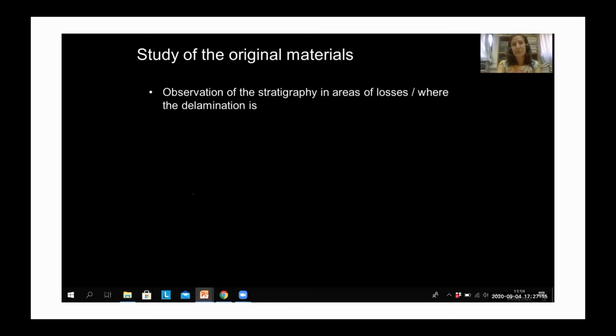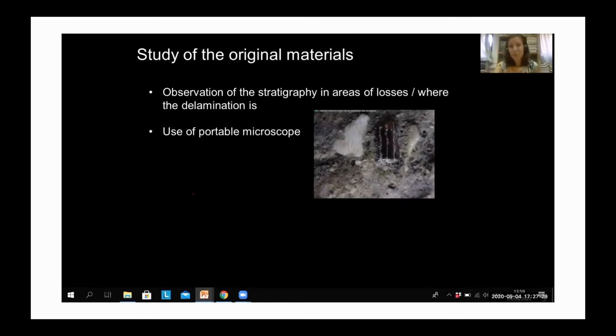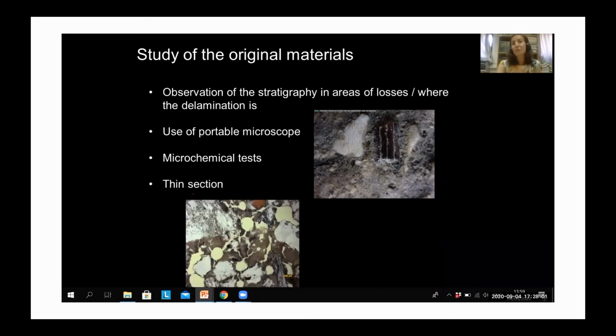And so in terms of study of the original materials, of course, we start with the observation of the stratigraphy in areas of losses, for example, or where actually the delamination is, if it's not concealed. We can use a portable microscope in order to look at the plaster, for instance, and to appreciate the size of the aggregates, to see if there are some inclusions. For example, this is a plaster in Malta with some local aggregates and with the presence of some shells. We can do microchemical tests in order to understand what the binder is, if that is not really clear, for example, lime or gypsum.